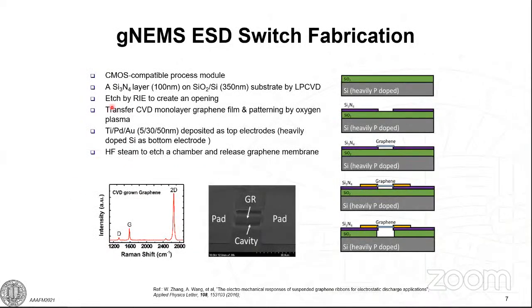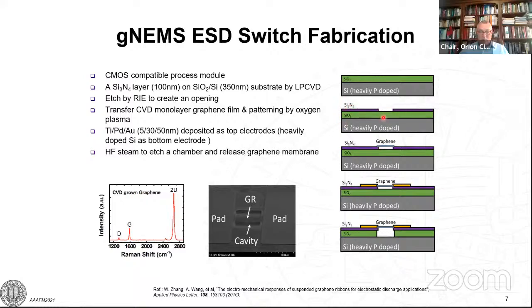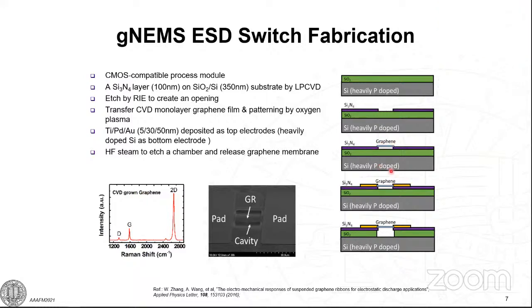Now, let's see how it works. This is the CMOS compatible process we developed, starting with the wafer, putting down some silicon dioxide and then silicon nitride, and creating the opening over here, and then transferring the graphene, and then using HF to etch the silicon dioxide underneath from the cavity, and eventually you will have this graphene gNEMS structure. This is shown in the image over here. You can see two pads over here, and the graphene ribbon is this one, and the little darker one underneath is actually the cavity. So let's see how it works.